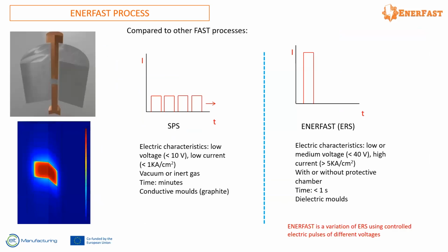Of course, there are more competitive technologies to this ENERFAST process we are developing. For example, one conventional one is spark plasma sintering. In this case, we are talking about minutes instead of seconds. In SPS, normally a graphite die is used. Then it's a hybrid heating, because you are heating the material, but also the die you are putting there. And for that reason, it is performed in vacuum and with moderate energies.